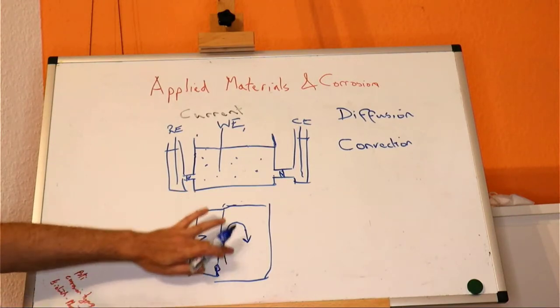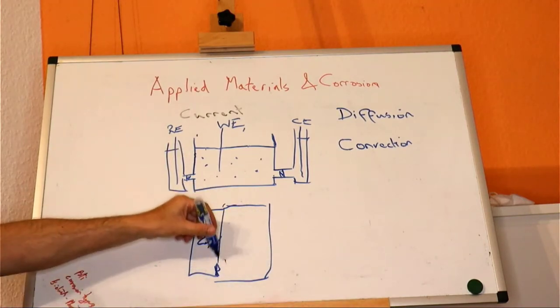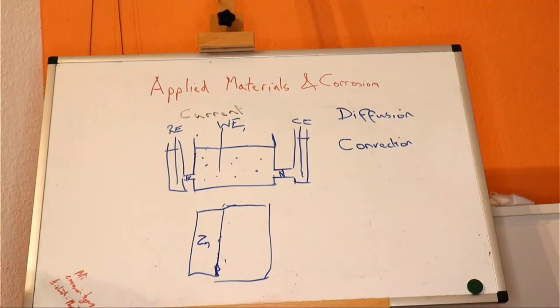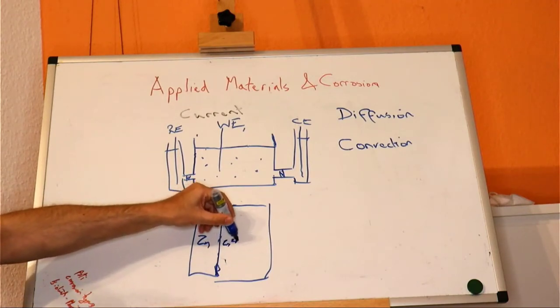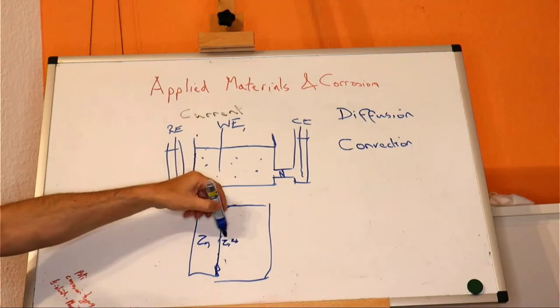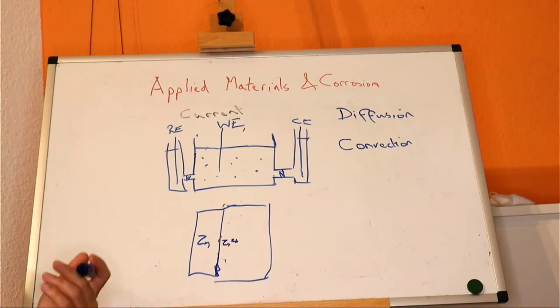So if I change my solution instead to a phosphoric acid solution, which is very viscous, or just add a lot of glycerol to my acid, we have to be a bit careful. If it's an oxidizing acid, if we add glycerol to it, we're in danger of causing an accident, but it is often used. We can certainly add a normal mineral acid or phosphoric acid, for example, to glycerol to increase its viscosity. And that will mean that when we make zinc 2 plus ions in solution, that will obviously make this area here less likely to dissolve, because the concentration of zinc 2 plus goes up, and so that's good.